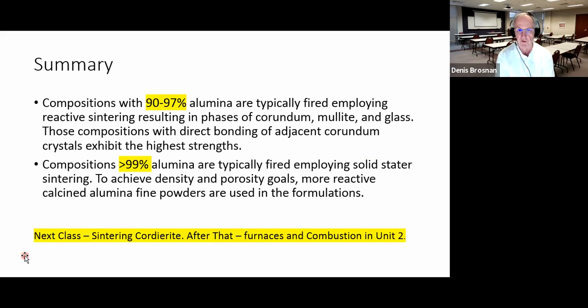So we looked at two examples, 90 to 97% alumina, those that contain a fair amount of silica that are reactive. Sintering takes place, forming mullite, a new mineral in the matrix. The glass may go away some or almost all. It may disappear in the sintering process. Then we looked at 99% alumina. And there we had an example where people played with the reactivity of the aluminum oxide to enable them to make the products at particular product standard goals.